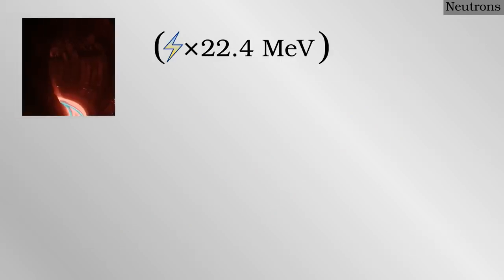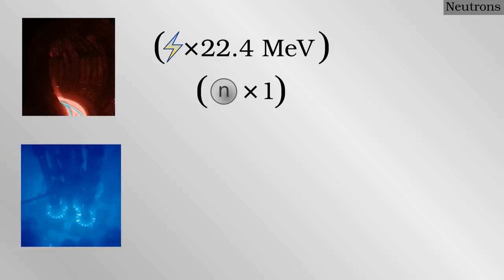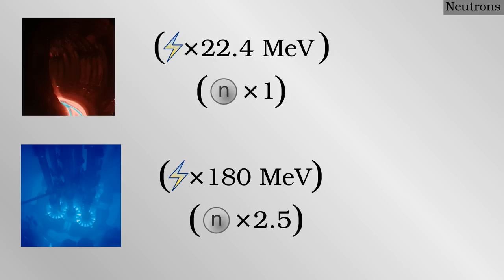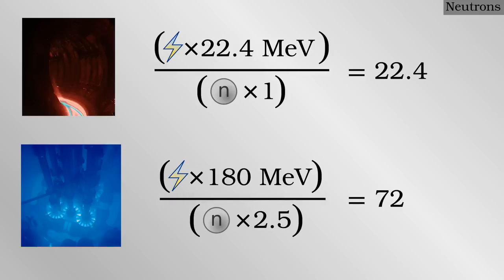Consider that deuterium-tritium fusion makes about 22.4 million electron volts of energy, involving just over 1 neutron. This is if we include the tritium breeding component I will get to in a moment. Meanwhile, common uranium-235 fission produces about 2.5 neutrons for an average energy release of 180 million electron volts. This means that for any unit of energy released, joules, kilowatt hours, and so on, fusion energy would produce 3 times more neutrons than a conventional fission reactor, all of them fast. Later on I will give some cases where this high flux of neutrons may actually be desirable. In general though, the neutrons pose a major challenge which must be overcome before fusion power becomes a reality.